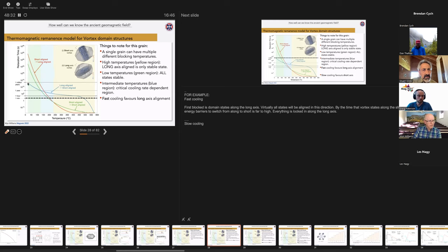Once we get into regions where the long axis grains can be reactivated, then some of those long axis grains will switch to short axes. And then we get this decrease of the PTRM at large PTRM temperatures. So in this instance, then this difference in blocking temperature from heating from below or cooling from above explains the reciprocity failure. And this decrease in the PTRM for increasing temperatures then explains this hook that we see at high temperatures. So these features of high temperature hooks and peaks in the high temperature PTRMs are not so unusual. And I've got one example here from a sample of basaltic lava from Hawaii that shows the same high temperature PTRM hook.